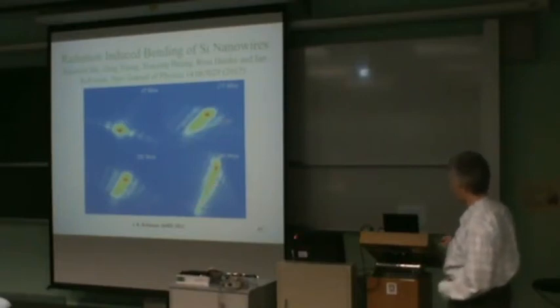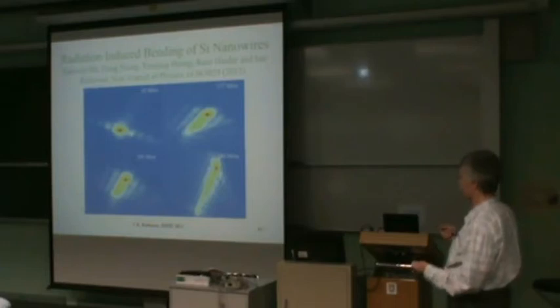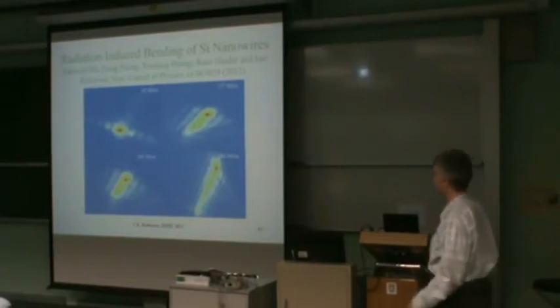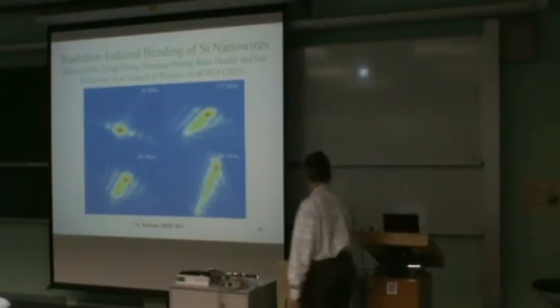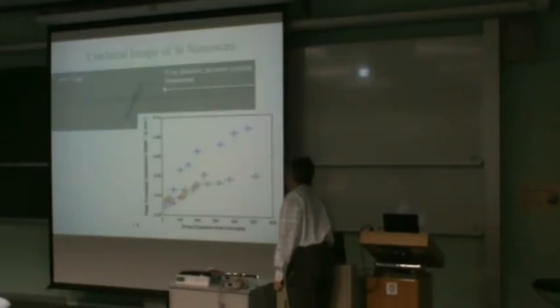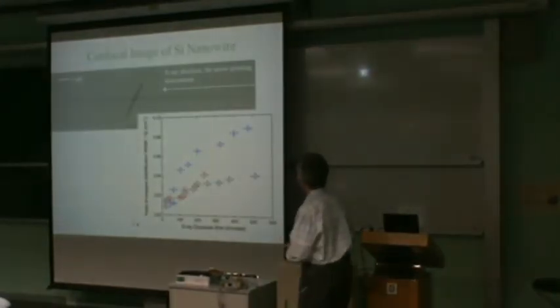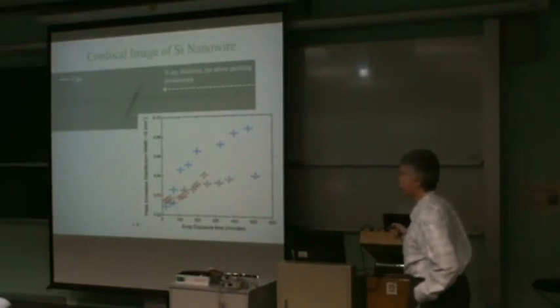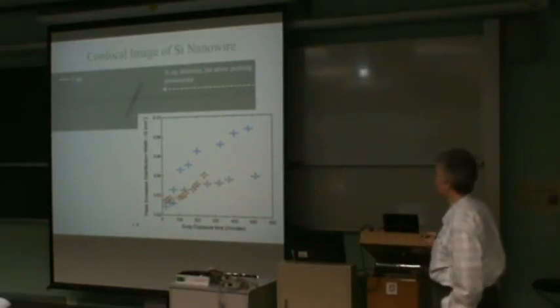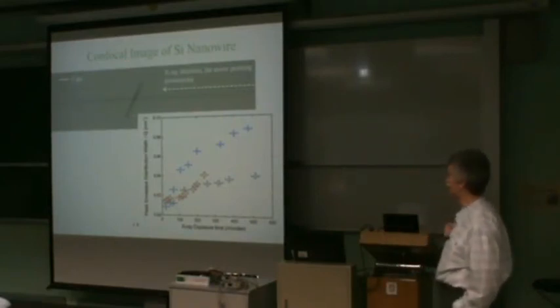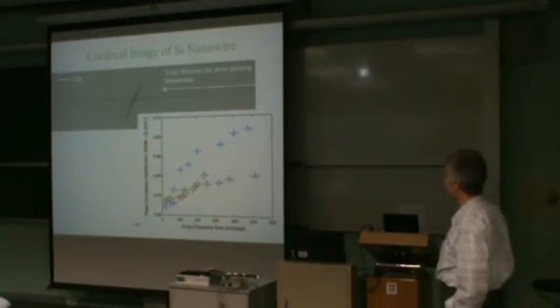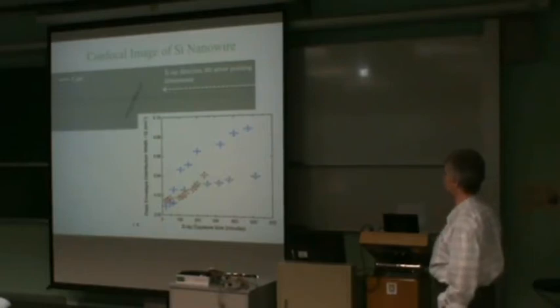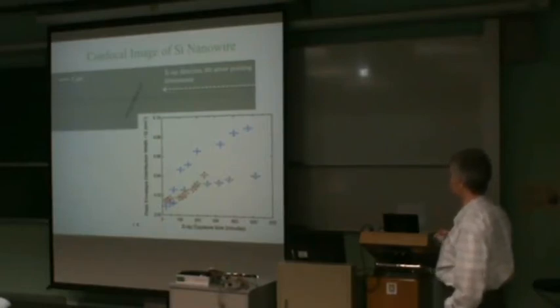And we've got a significant amount of strain starting to appear in the wire just by exposure to the X-ray beam. And what is going on is that it's not the wire which is becoming damaged by the X-rays, it's the oxide which is becoming damaged by the X-rays. And many other people have seen the same thing, that silicon oxide is actually rather unstable to X-ray exposure.